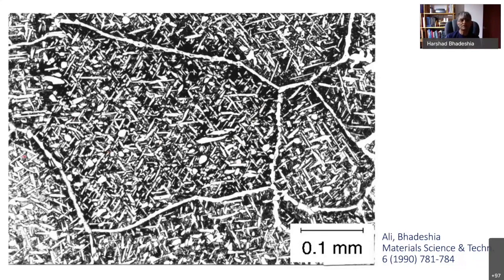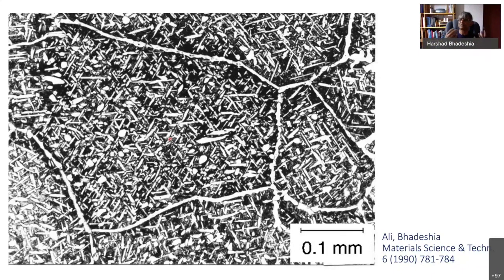There isn't a single phase here — we have two different kinds of ferrite, and they have different kinetics and thermodynamics. So you should imagine this as two different phases forming in the austenite competing with each other. Whichever phase wins will have the greater volume fraction inside the steel. So, how do we tackle the formation of several phases at the same time?